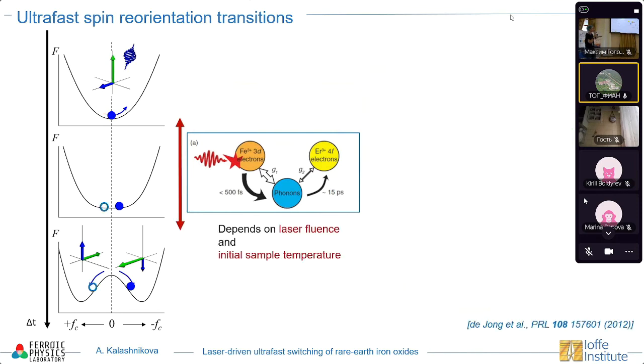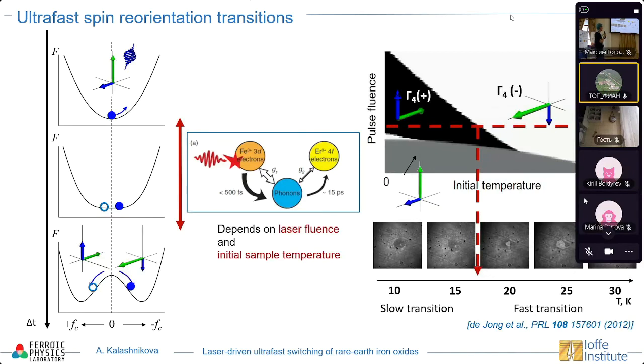What is interesting is that the time required for this repopulation of the rare earth states and for the emergence of these two minima was shown to depend on laser fluence and on initial sample temperature. And we can imagine that if this time is longer than the half period of the excited precession, the system will go first here, then it will go here, and it can end up here. So by changing the fluence or initial temperature, we can also go to this state or to this state. And we did some modeling, and we showed that indeed it is possible.